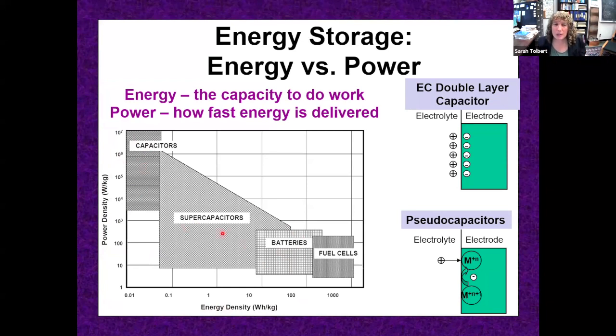Something that bridges the gap is something called a supercapacitor or an electric double layer capacitor. And this is a high surface area conductor where you charge up one plate of the conductor and then you balance the charge by an ion in solution. So you make a little set of parallel plates at the liquid solid interface. So this is like a parallel plate capacitor, except it has much higher surface area, so much higher energy density.